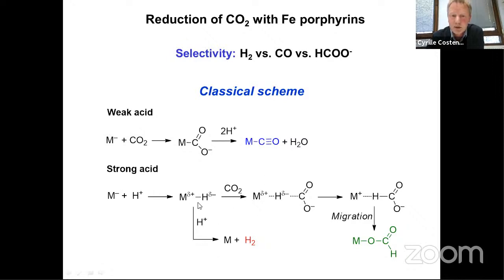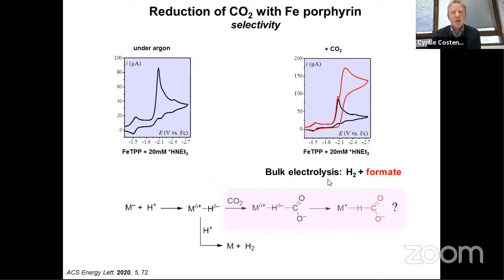And if it reacts with CO2, you might end up making formate. And so you could change the selectivity. So here is the experimental example where you have iron porphyrin and an acid. The reaction is very fast. You make hydrogen. As you can see, you have a sharp peak because you're in total catalysis. You consume all the acid during the CV.